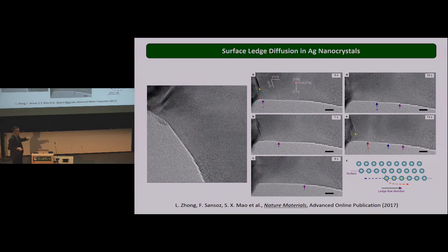Right? So the advantage of using the experiment is we're now at the point where we can look at the atom dynamics on the surface of the wires, and that explains a lot, especially trying to understand the difference in mechanical behavior. So basically what you will see here are single crystal slip events, so some surface dislocation. And each time you nucleate a dislocation, there's a tiny atomic step that forms on the surface. And so we were able to capture the dynamics of that step in almost real time. There's about half a second of time between each snapshot, so it's pretty slow. But you'll see on the movie here that process.